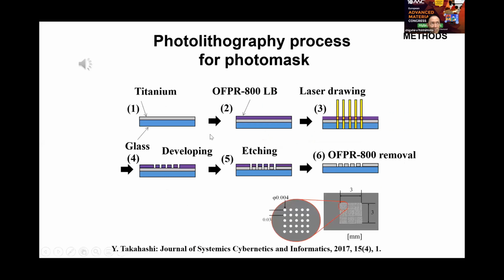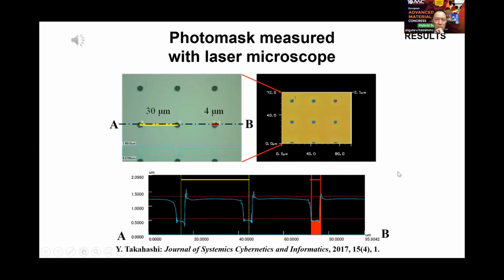The slide shows the photolithography process to make the photomask for arrangement of micro-protrusions: titanium coating, photoresist coating, laser drawing, developing, etching, and photoresist removal. After many trials, dimensions have been selected for markers and thin film thickness. Dimension of the manufactured photomask was measured by laser microscope, which shows the diameter of each marker as 4 micrometers, and the interval between markers as 30 micrometers.